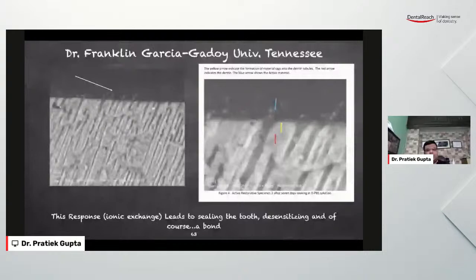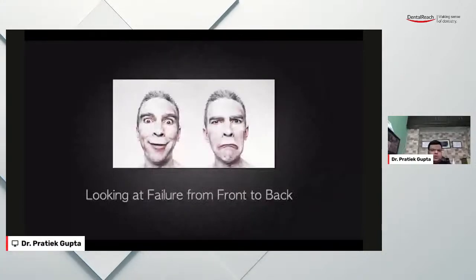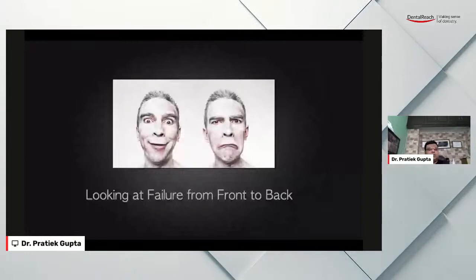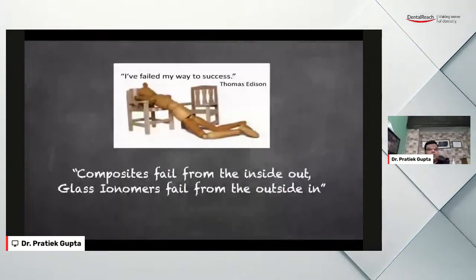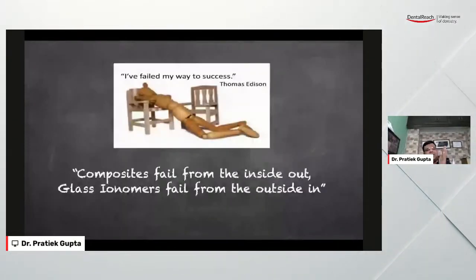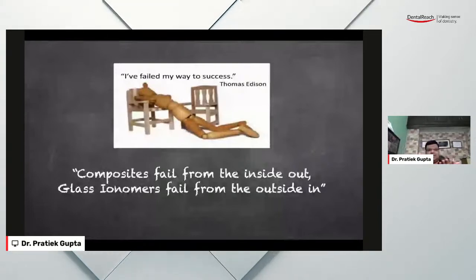Again, see how deep those resin tags start forming. Now, if you look at failure from front to back, especially with composite resins, composites fail from inside out. That means composites fail from the bonding layer. But if you look at glass ionomers, they fail from outside in. They get desiccated, they get broken, they dissolve in saliva, but they never fail on the bond layer.